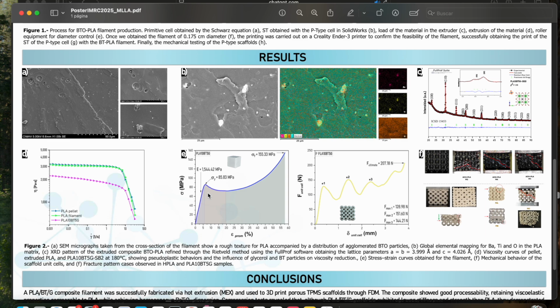The filament-level mechanical response establishes the baseline for scaffold performance. Tensile stress strain curves show the composite retains viscoelastic characteristics comparable to PLA, with a moderate reduction in stiffness and strength that is typical for filled, plasticized systems. The retained ductility and compliant matrix are important to enable controlled, non-catastrophic collapse during lattice compression.